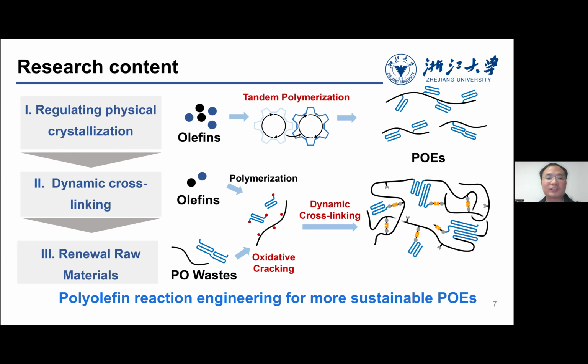During the last decades, in our lab, we did a lot of work. First, we tried to regulate the physical crystallization in the polyolefin elastomers, trying to get a high-performance polyolefin elastomer with a short process. Recently we introduced dynamic cross-linking into the polyolefin elastomer, trying to still have a high-performance polyolefin elastomer that can still be processable. And most recently, we think maybe we can use polyolefin waste or new raw materials, crack them to oligomers, and based on dynamic cross-linking, synthesize high-performance polyolefin elastomers with this raw polyolefin waste as raw material.